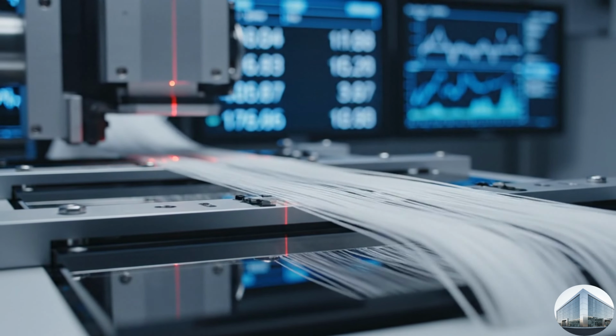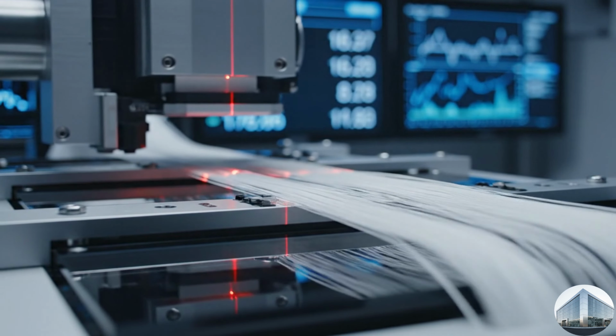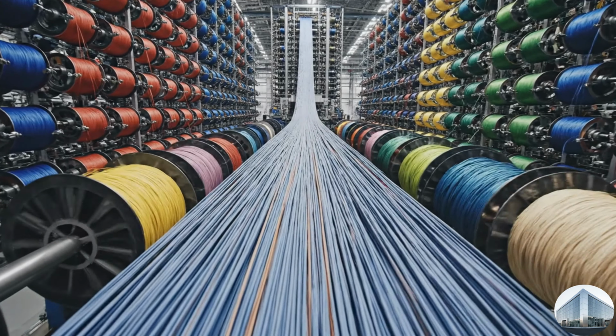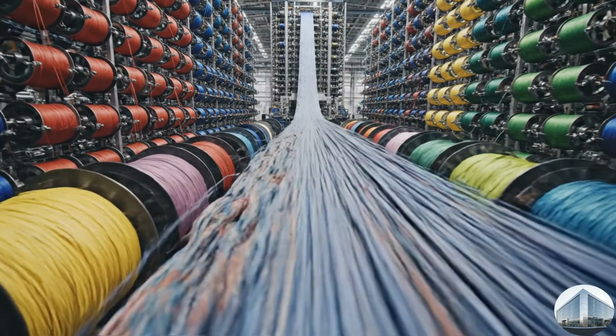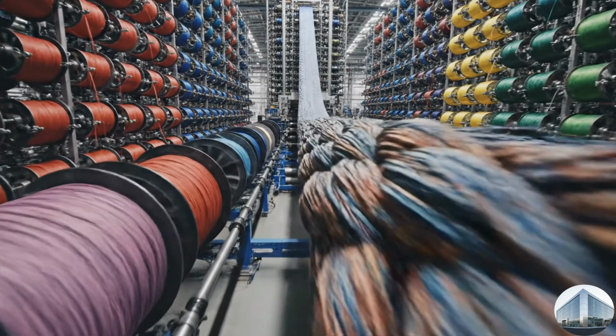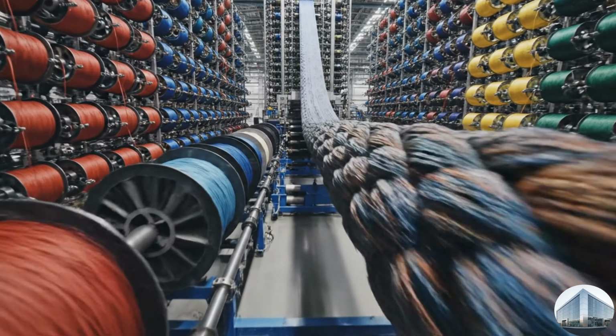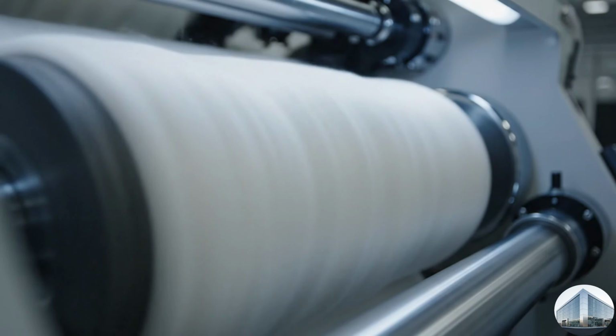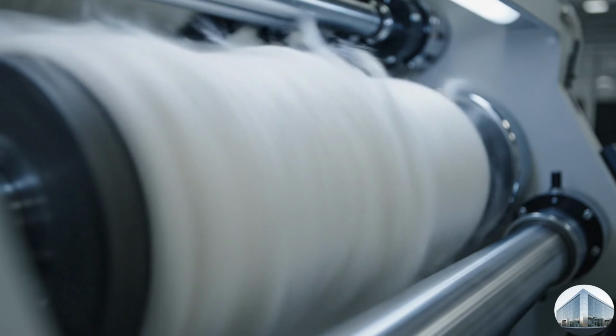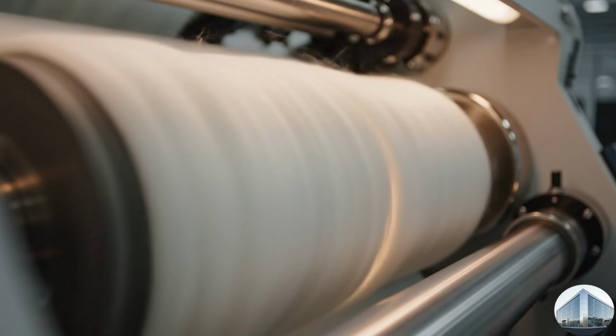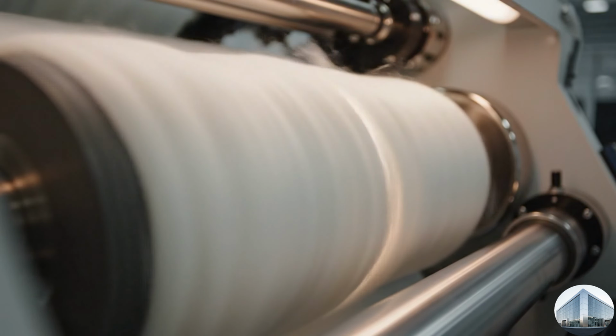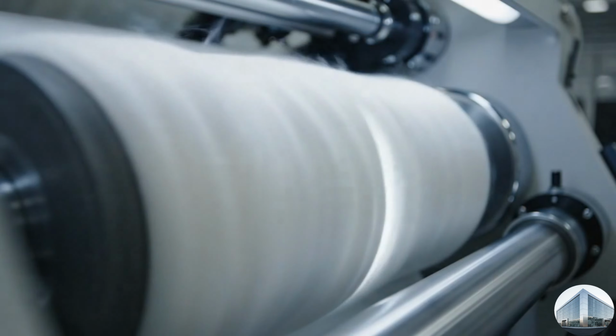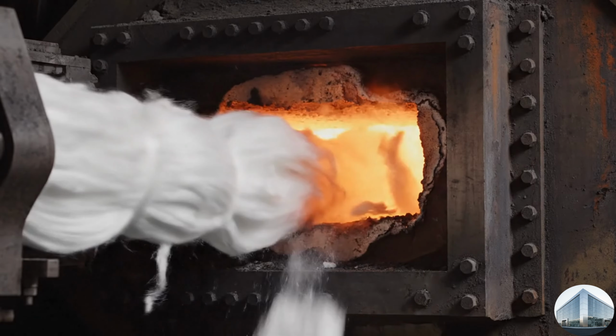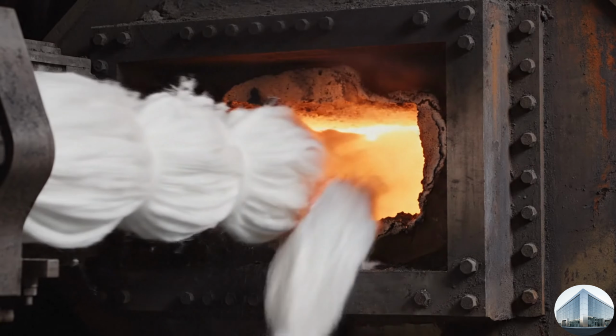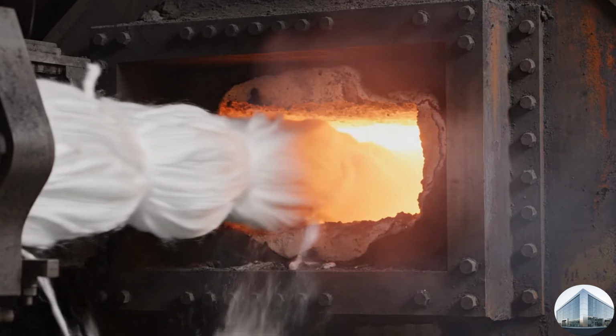The sheer scale of the creel room is breathtaking. Thousands of individual threads come together, yet moving as one toward the furnaces where their molecular fate will be sealed. Speed and tension are perfectly calibrated. This mechanical ballet ensures that every inch of the precursor material is ready for the intense heat that lies ahead in the ovens. As the white fibers disappear into the first furnace, they leave behind their polymer origins. A new, much stronger structure is about to be born through controlled oxidation.